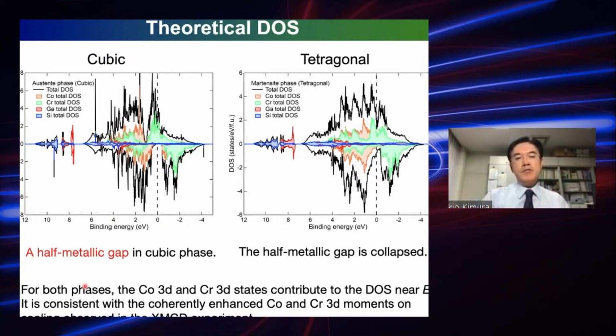Anyway, for both the cubic and tetragonal phases, the cobalt 3d DOS is drawn in orange, and the chromium 3d DOS is represented in green. So you see contributions from both cobalt 3d and chromium 3d states near the Fermi energy. And this is consistent with the experimental result of the XMCD. You see the similar enhancement of the cobalt and chromium 3d magnetic moments.